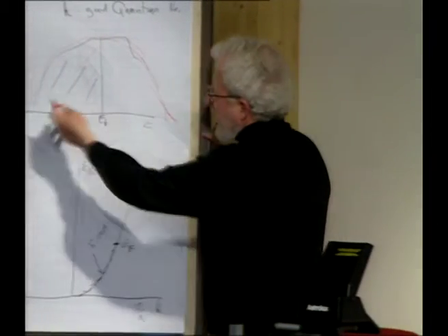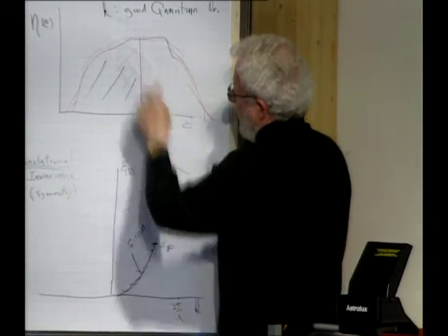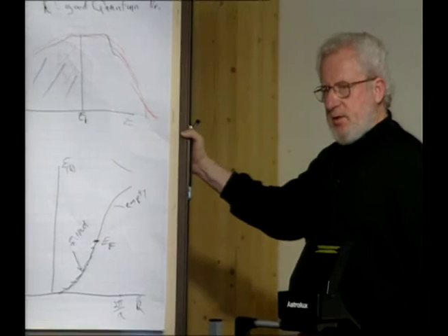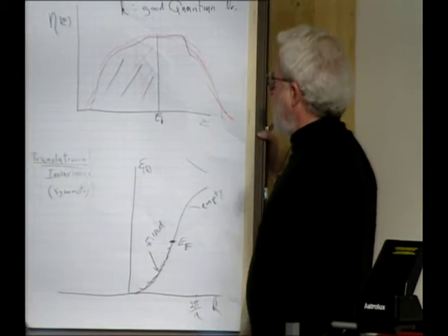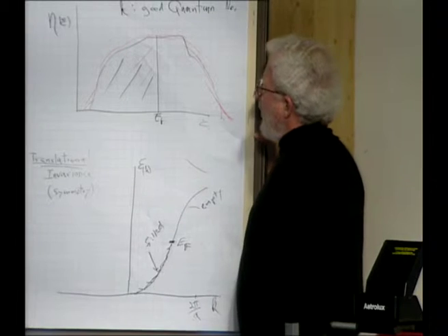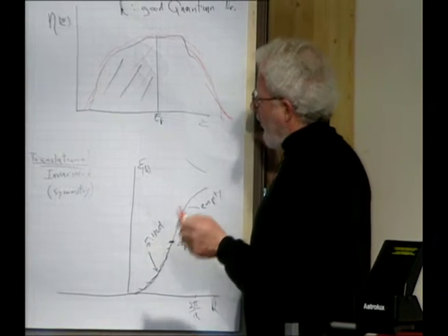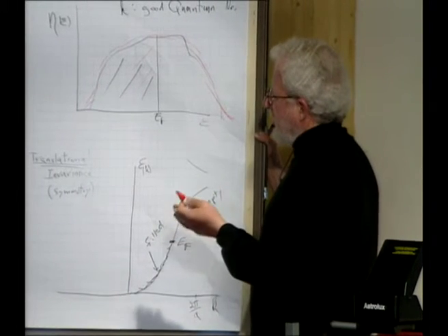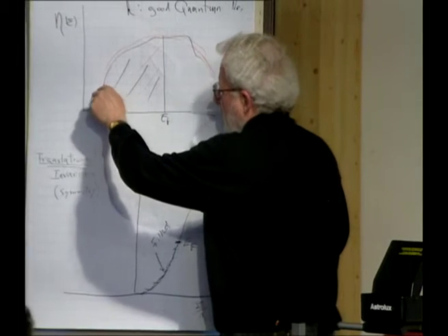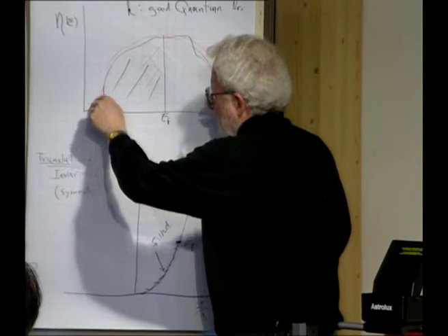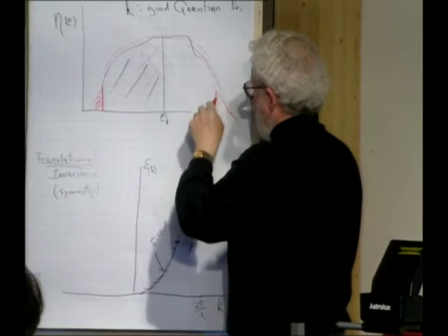This is the density of states, and if you integrate the density of states, you get the number of electrons. The number of electrons doesn't change if you put in a little bit of disorder, even a lot of disorder. But what happens is, gradually, as you increase the strength of the disorder, these states get localized. And these states get localized.